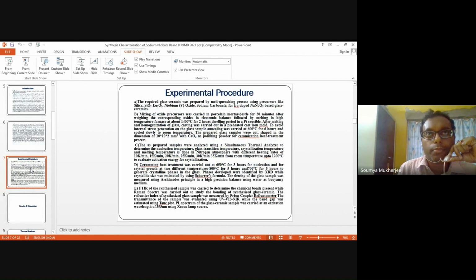So it's a very much solid state synthesis, where we are taking the oxides mainly: silica, europium oxide, niobium pentoxide, and sodium carbonate as the sources for silicon, europium, niobium, and sodium, for making the sodium niobate based system. That is the europium doped system. The oxides have been taken.